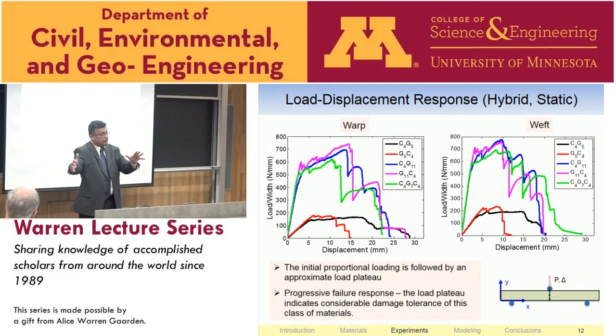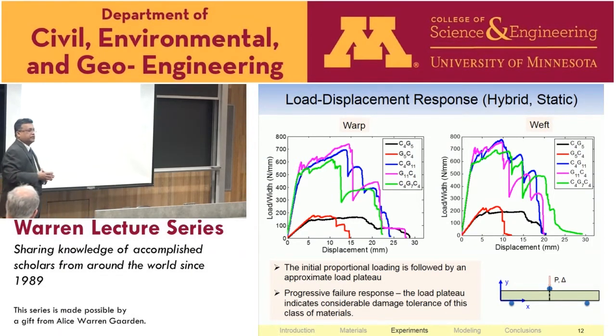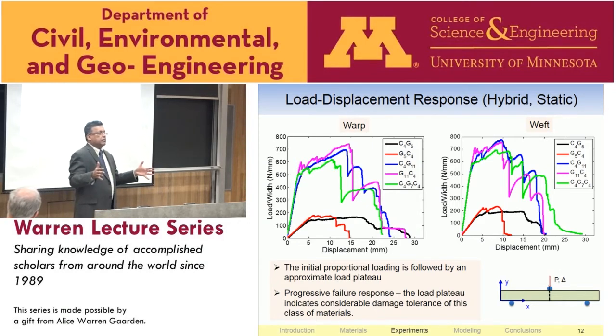So the point I'm trying to make is that you can actually tailor the structural performance of the front end to impact what the head acceleration levels of the occupant is in a vehicle. That you can't do very well with, let's say, a monolithic material unless you have lots of geometrical control, because we know that geometry can also help us. But if you have material control, material microstructure control, you have that additional advantage that you can design the geometry of the larger structure, but tailor the microstructure as well.